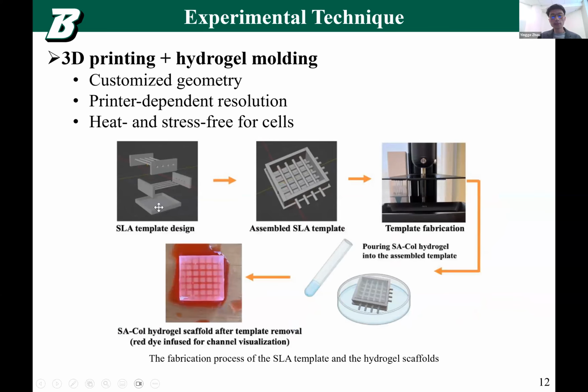And then we developed a 3D printing structure to just print the vessel or the channel structure. Here is a simple channel structure. This is the 3D model, and then we stack them together and print it using an SLA printer. SLA has pretty high resolution. We can also print it with FDM, as long as the material is dissolvable in water. Then we create a mold, and then pour the hydrogel into the mold, and let the hydrogel cross-link, and then dissolve the mold in the water. Then the hydrogel, after cross-link, is going to form some channels within the hydrogel. And the shape, geometry, and resolution of this channel, we can control.